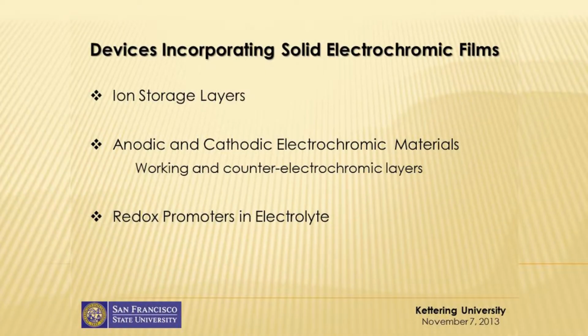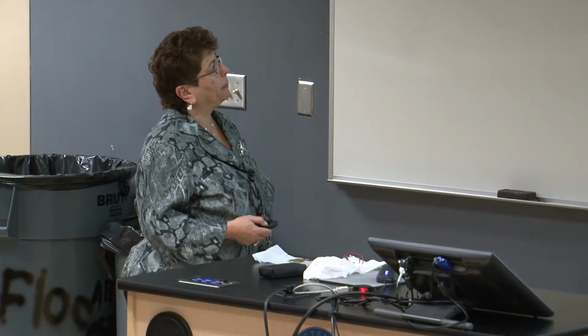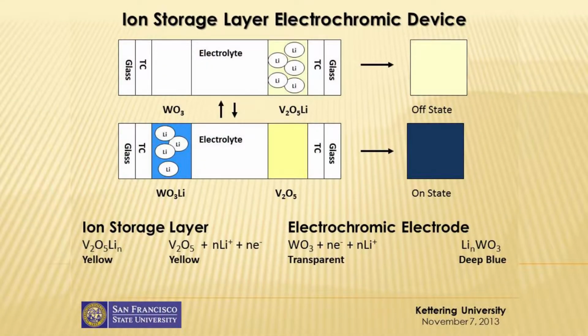Now, devices incorporating solid electrochromic films consist of an ion storage layer, and anodic and cathodic electrochromic materials. I call them complementary materials: a working electrochromic layer and a counter electrochromic layer. Redox promoters in the electrolyte. This is a sample of this type of device. The ion storage layer electrochromic device consists of glass and transparent conducting layer coated glass. There is an electrolyte between them in the center, and we have a working electrode and a complementary electrode here. In this case, I give an example using tungsten oxide and lithiated vanadium pentoxide.